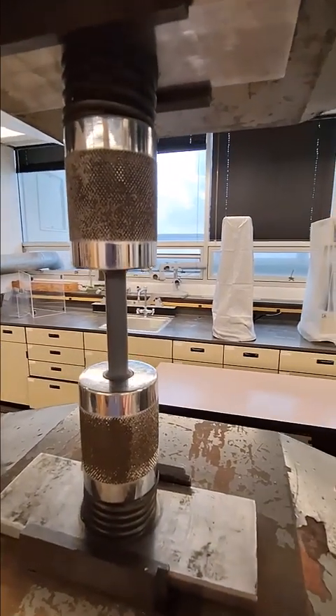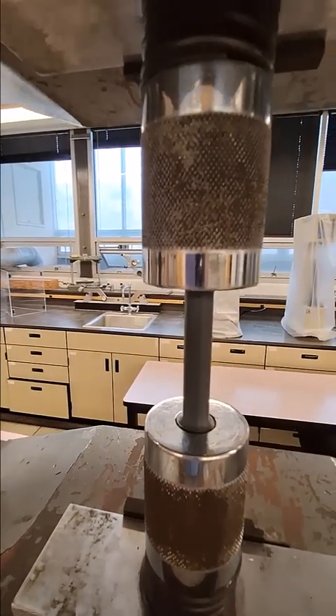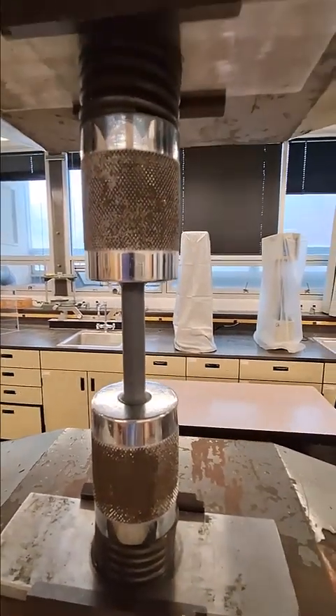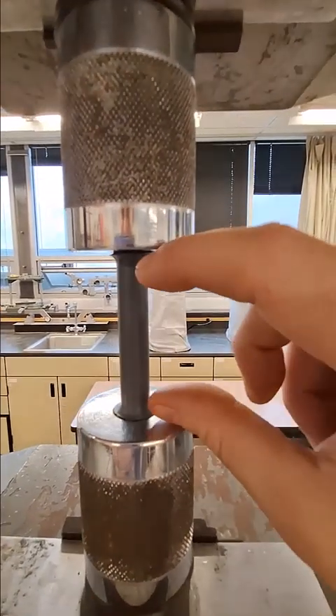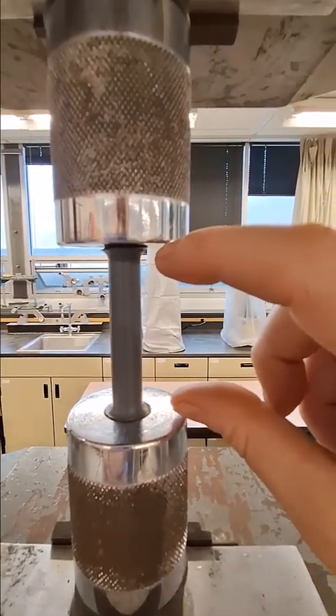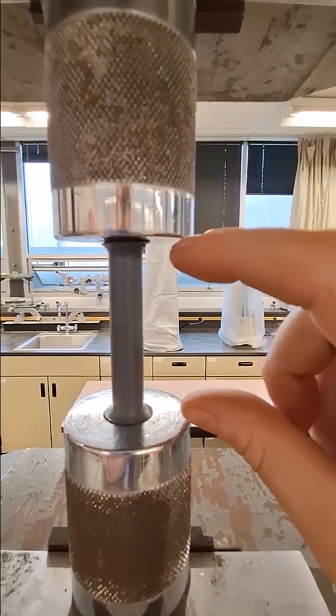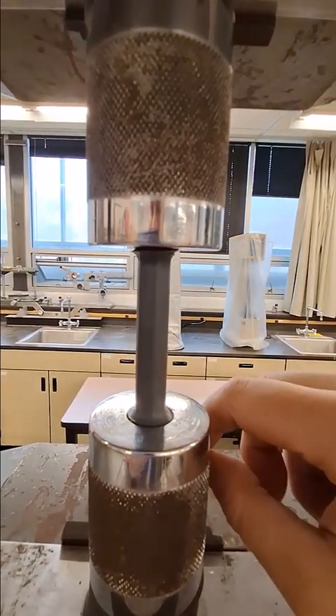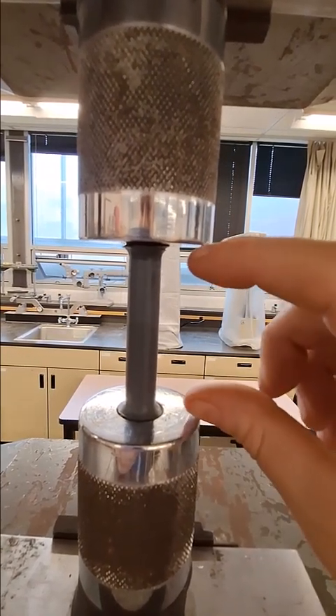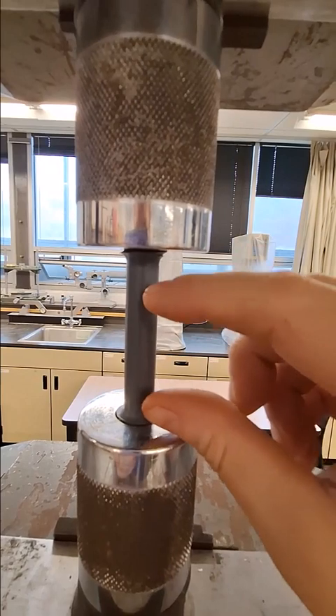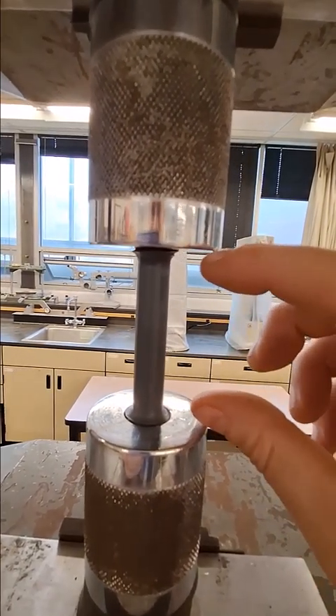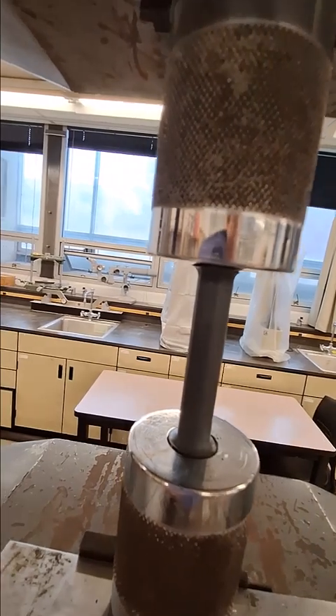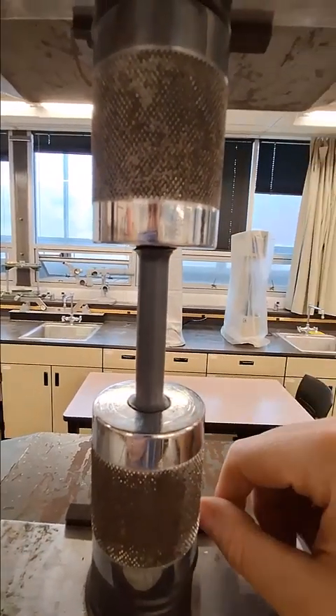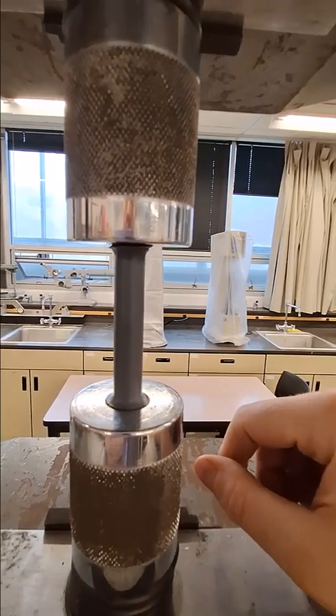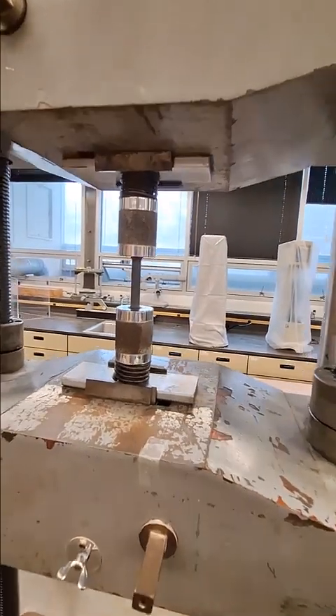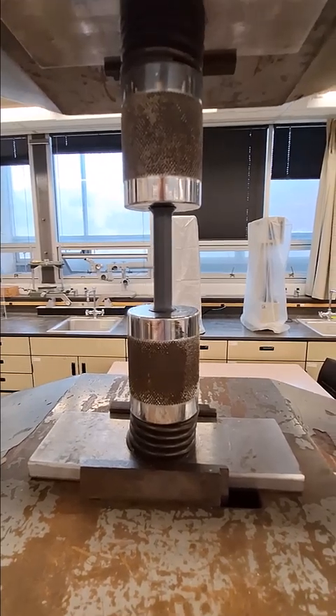For our actual test, we're going to take data with an extensometer, so we don't really have to measure the initial gauge length. But if you're doing an old-fashioned measurement, you would measure your gauge length, the initial length of your sample, with the micrometer. It'll be fine if you're looking at ultimate tensile strength, yield strength, some of those values, but for calculating a Young's modulus, there's going to be an initial error, because you want to be really accurate in those first couple of steps of displacement of your jaws. So an extensometer is really the best way to measure those values. But we are using this to get a sense today of how we're going to run this experiment.